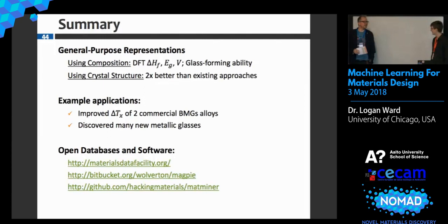Anything else? So then in the model that you trained in this example, how did you incorporate the information that you had, these two different data sets that came from the two different casting methods? The first approach we used was to add a variable that would describe which data this came from: one if sputtering, zero if melt spinning. We ended up finding that it would be better to, rather than include that single variable, which in the 140 other variables in the model doesn't come through as very important,